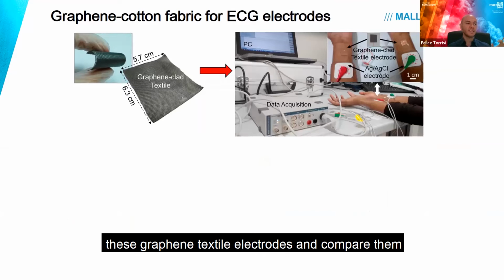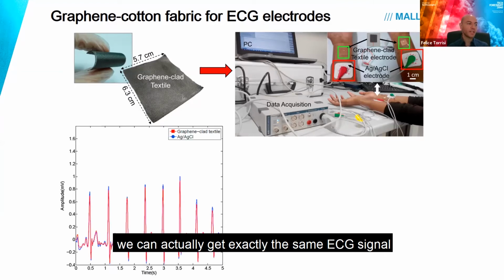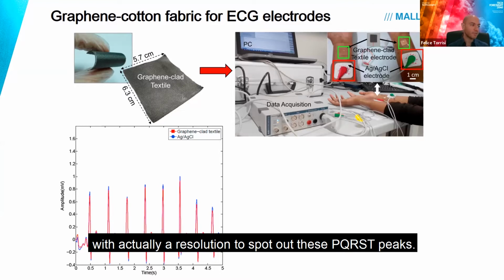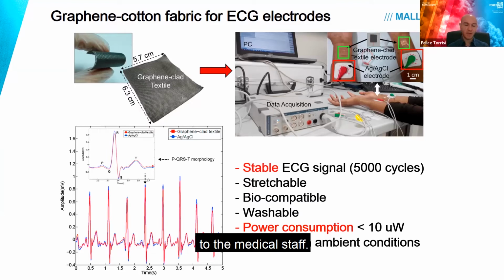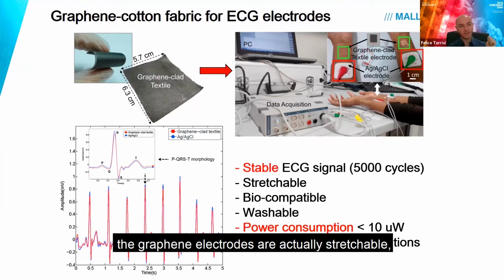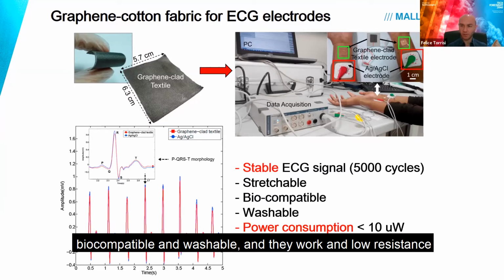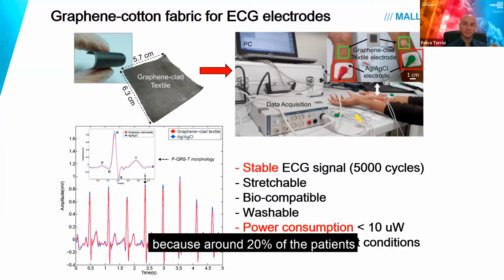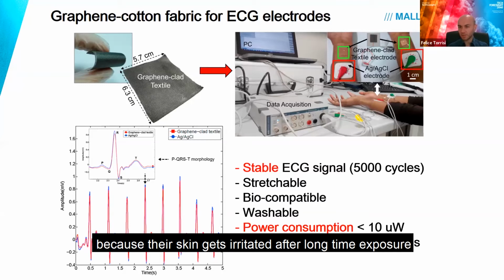So we use, for example, these graphene textile electrodes and compare them with standard ECG electrodes. You might know ECG electrodes. They are rigid electrodes that normally are placed on top of the skin. They are made normally of silver chloride. And then what we did, we compared it with graphene textile electrodes. And surprisingly, but extremely importantly, we can actually extract exactly the same ECG signal that you would extract with silver chloride electrodes, with a resolution to spot out these PQRST peaks, typical of ECG and very important, for example, to the medical staff. With a big difference that these devices, the graphene electrodes, are actually stretchable, biocompatible, and washable, and they work at low resistance or low power consumption. This is also very important because around 20% of the patients actually can't undergo standard ECG because their skin gets irritated after long exposure to the electrodes.